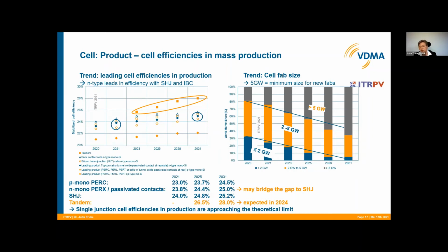And in 10 years, the N-type PERCs with passivated contacts like TOPCon would be very close to the silicon heterojunction with about 25.2%. And the only possibility to overcome the limit on the single junction is the tandem, and we see here that the tandem is expected in 10 years with about 28%.